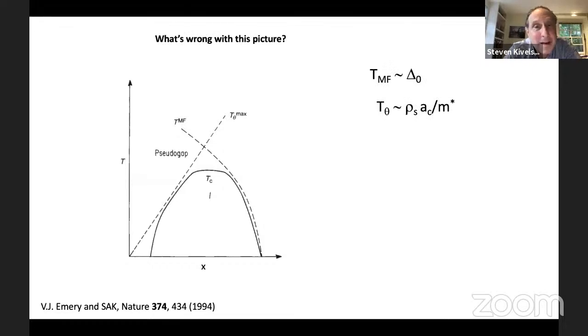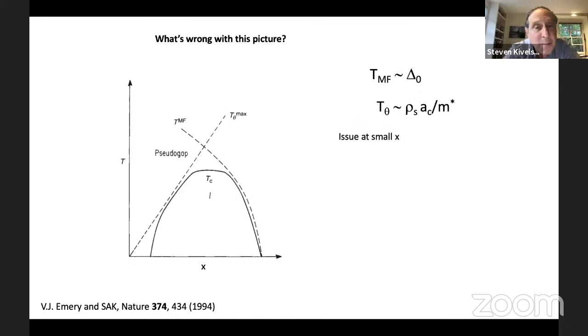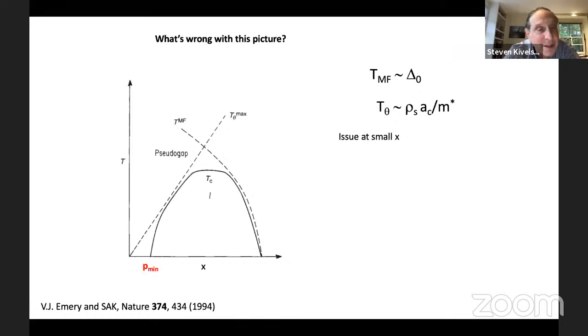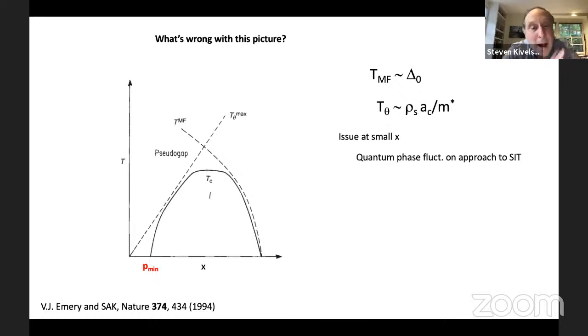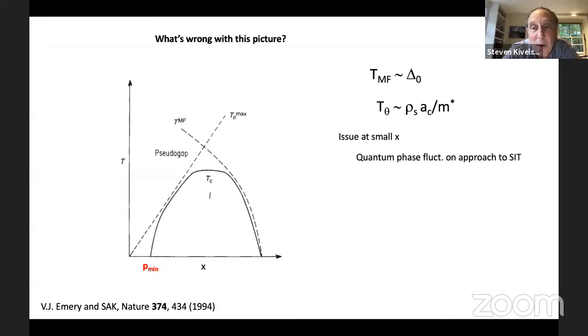What's wrong with this picture? The first issue was clear at the time: the picture was wrong at small X, where the dashed line only goes to zero at X=0, whereas the actual superconducting TC goes to zero at some minimum doping. That's probably associated with quantum phase fluctuations and possibly with the approach to a quantum superconductor-to-insulator transition. There was also the so-called boomerang effect: the superfluid density increases with increasing doping to a little past optimal doping, but then tends to drop again as one approaches the overdoped side of the superconducting dome.